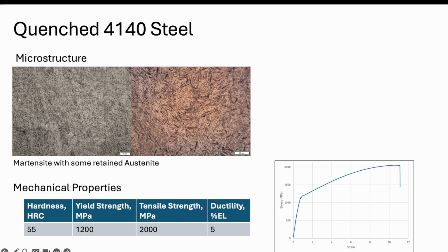Other things about this, from the engineering stress strain curve, we have a yield strength of about 1200 and a tensile strength of about 2000. The ductility can vary, but we tend to get an average of about 5% elongation. So it doesn't extend a lot. That's what we see with martensite: it tends to have the extremes. It is the strongest, has the highest values of strength and hardness, but has the lowest ductility, meaning it's the most brittle structure we have. That's actually a problem, because in some cases it's too strong and it can fracture in a brittle manner.